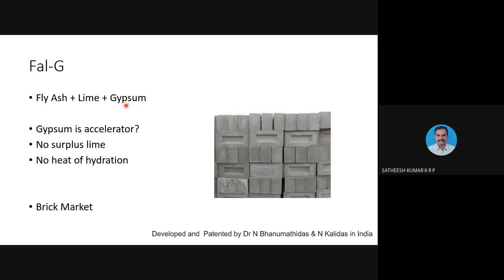This combination of fly ash, lime, and gypsum is more suitable for 3D printing rather than conventional concrete. Even though we can use some additional accelerators for cement, that is also possible, but the most preferred is this fly ash and lime combination. With the variation of the various grades of fly ash, sometimes they also need compressive force. We need to apply some initial pressure as well as temperature for curing for some forms of the combination of these materials.